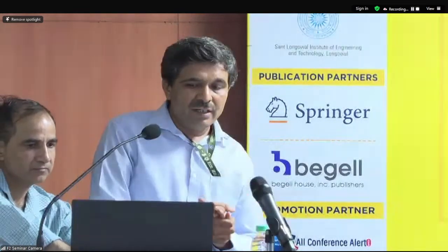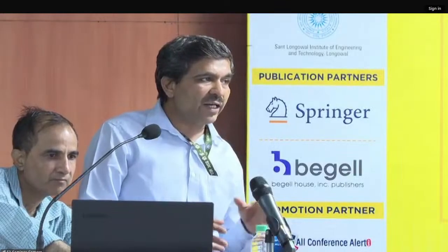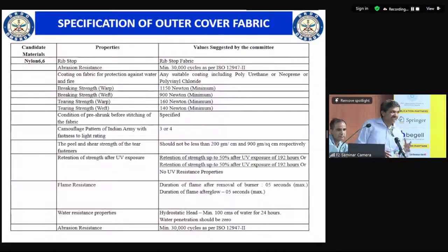These are in the table here, and when we see the picture of the bulletproof jacket, the outer fabric of the bulletproof jacket also plays a very important role, because it has to stop the API bullet, which is called armor piercing incendiary. The bullet has a special coating of phosphorus which creates an incendiary effect, means upon impact it will try to create a spark, and if the fabric is not a fire retardant fabric, there will always be a probability of the bulletproof jacket catching fire. So the outer carrier, which is the housing of the hard armor panel, also plays an important role, and these are a few of the important things that need to be addressed while we are using the material.